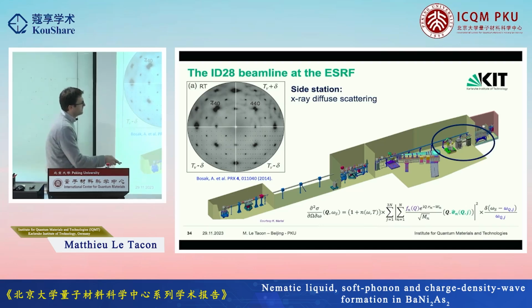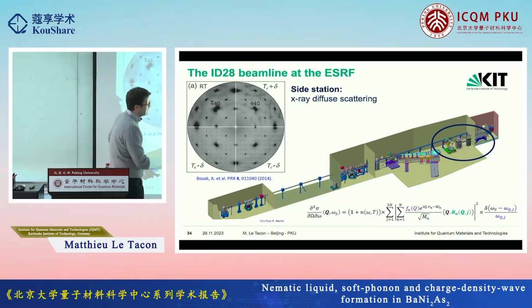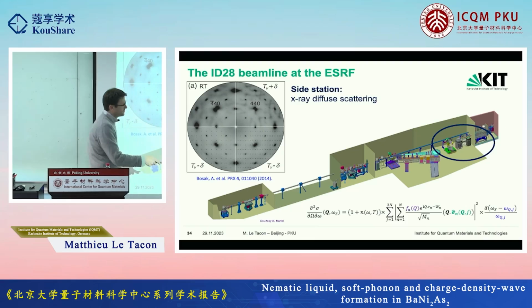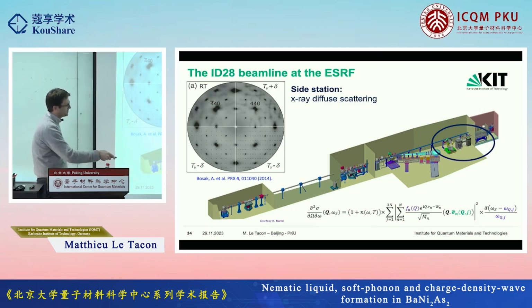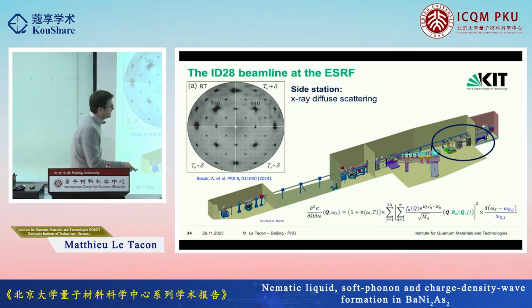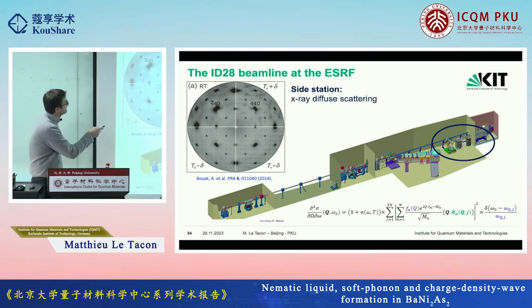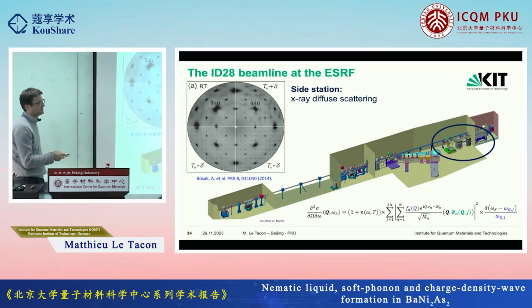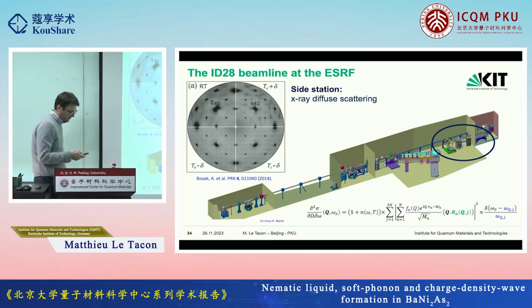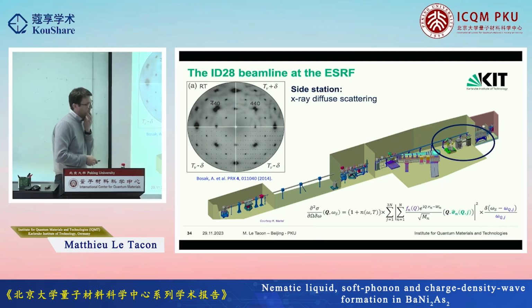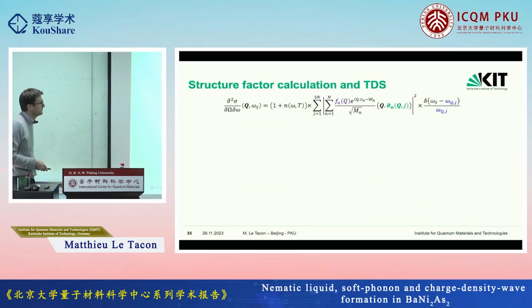And you have this delta function which picks up the phonon at the energy where it is. Now there's this 1 over omega term, which means that if you integrate over the energy here, if there is a phonon that is softer than it should be in the dispersion, it will appear as some trace in your diffuse scattering map. So this is just the energy-integrated part of this thing. So we can use this to locate ourselves in the reciprocal space before starting to look at the